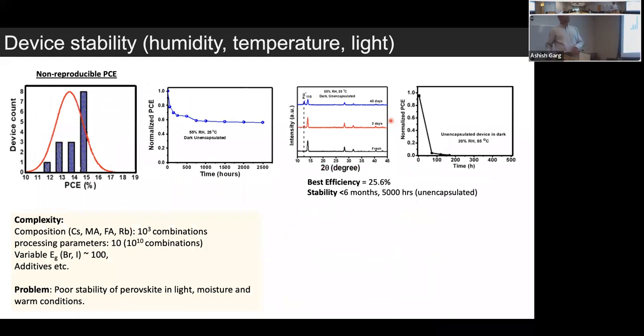One of the issues that we see in our lab is a problem with reproducibility. If you make several devices, the devices tend to show efficiencies which could be on the higher side of 15 or the lower side of 15, but the spread is large. So you get a bell curve which is pretty